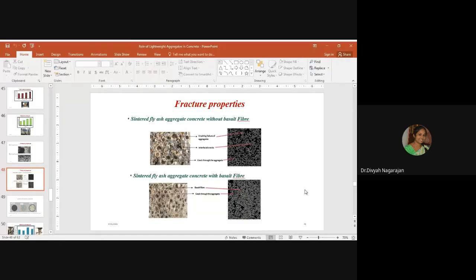It is because of the excellent aggregate paste bond present between the cement and the lightweight aggregate matrix. The fracture plane passes through the aggregate instead of bypassing it. It can be seen from the figure.